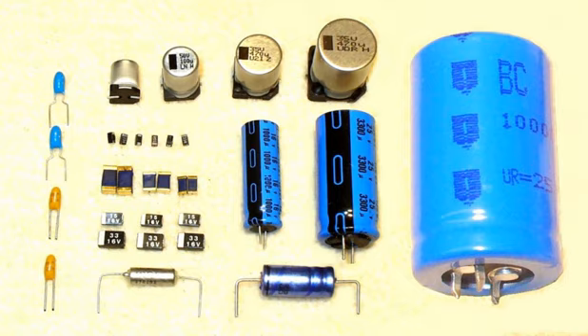In his 1896 patent, Pollak already recognized that the capacitance of the capacitor increases when roughening the surface of the anode foil. Today, 2014, electrochemically etched low-voltage foils can achieve an up to 200-fold increase in surface area compared to a smooth surface. Advances in the etching process are the reason for the dimension reductions in aluminum electrolytic capacitors over recent decades. For aluminum electrolytic capacitors, the decades from 1970 to 1990 were marked by the development of various new professional series specifically suited to certain industrial applications, for example with very low leakage currents or with long life characteristics, or for higher temperatures up to 125 degrees Celsius.